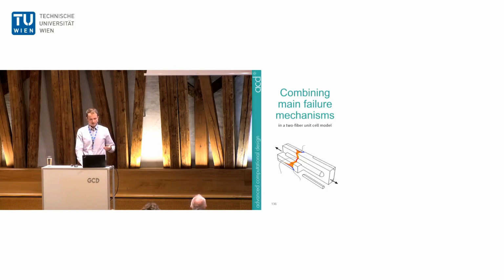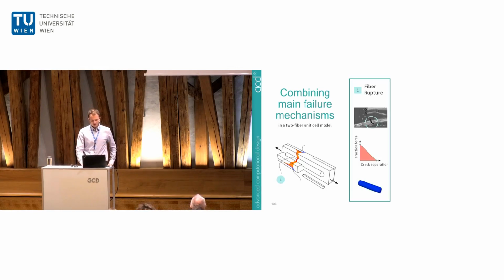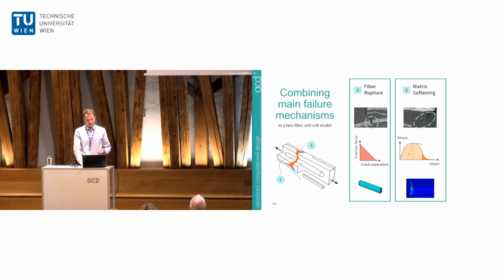So now we've defined the geometry of the model, and now we try to find some laws to replicate the observed behavior of the composite. For the fiber rupture, we have the so-called traction separation law, which basically says if a certain stress level in the fiber is exceeded, then a crack is initiated, and this stress then gradually decreases until the fiber gap is fully opened. And we define quite similar material laws for the other effects, for the degradation of the matrix and for the debonding of the interface.